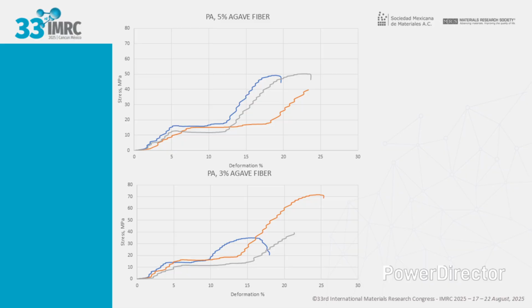The intermediate curves suggest localized yielding or the appearance of progressive damage mechanisms, microcracking, matrix-fiber debonding. The 5% graph shows that the fiber improves initial stiffness, but introduces heterogeneities that limit maximum strength and maintain more brittle behavior. Consistency between repetitions indicates good reproducibility.